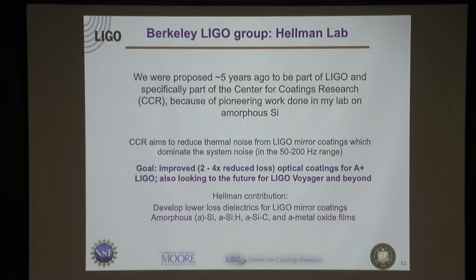It's an interesting one because it's very easy to make by vapor deposition processes, which is what I do, but you actually can't quench it. If you make liquid silicon, it's rather like water. If you take liquid silicon and you cool it down, the liquid is actually denser than the crystalline phase. So like water, where the crystalline phase floats on top, right? Ice floats on top of water because it's less dense. So silicon has the same thing. So when you try and quench the liquid state into a glassy state, what happens is it just nucleates crystallites. The energy is too high and it doesn't remain amorphous.